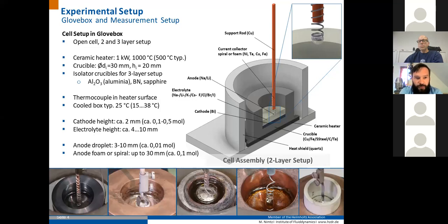We have several different setups. Most of these are completely open cells, which means we can look into the cell and observe the 2 electrodes and the electrolyte in parallel. And we managed to install the 2 and 3 layer setup for different cells. 2 layer setup is basically 2 layers of the lower electrode and the electrolyte above, where the 3rd electrode or the 2nd electrode is held by a rod or a nickel spiral as displayed here.